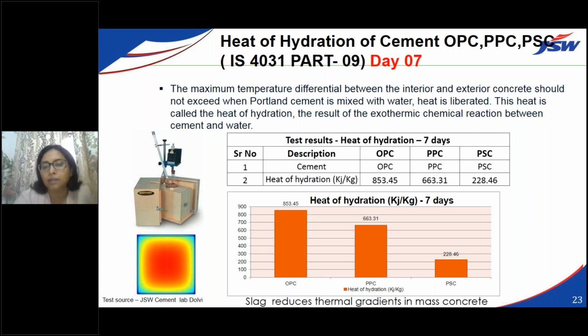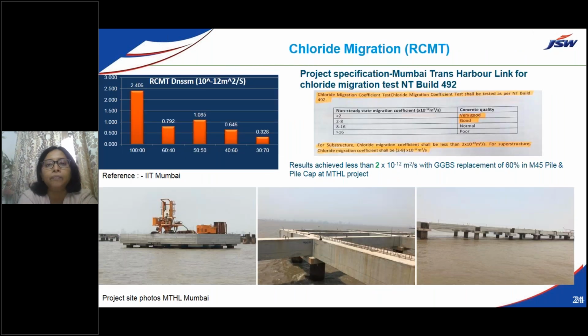So you can see the thermal gradients of the mass concrete are reduced. The temperature of the concrete goes down. There will be very less cracking in the concrete structure. And again, going back to the same thing, the durability of the structure will be improved. The exothermic chemical reaction, when water is added to cement, there is a lot of heat which is getting evolved. So that thing can be controlled with products of slag. Very important parameter. This is a new parameter which has come in and which is very much prevalent.